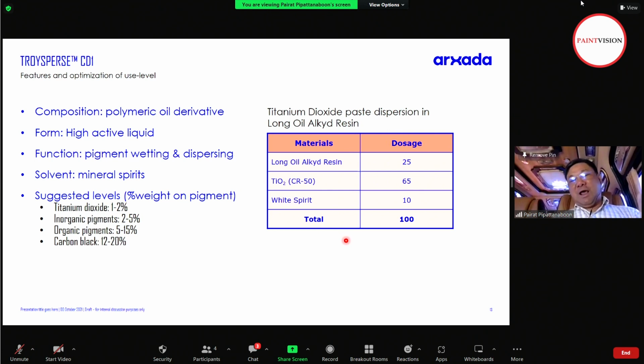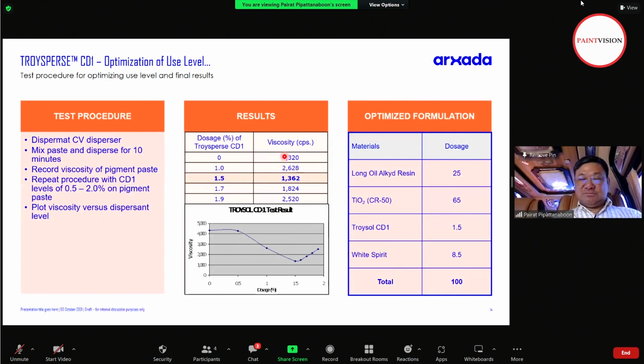We tried in the lab to study how to optimize CD1 in a long oil alkyd resin with 65% TiO2 loading. All right, so it's mineral spirit, long oil alkyd resin, and TiO2. From the optimization, we slowly increased the dispersion, and we found that CD1 at 1.5% on total formulation gives you the lowest viscosity.